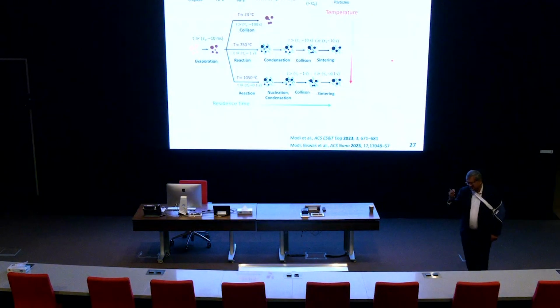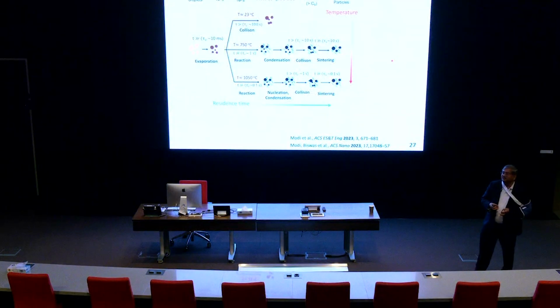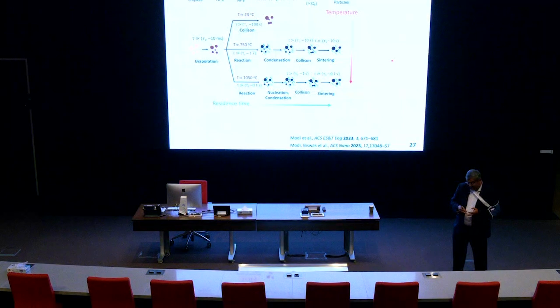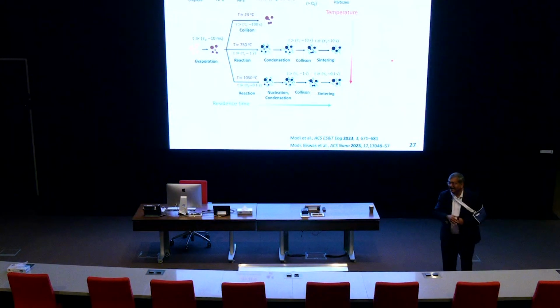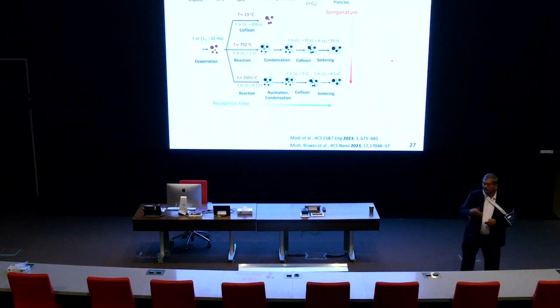So this creates a little bit of a challenge for me to understand. Yes, so in some sense you're absolutely right. Would a pure carbonaceous particle sinter, right? Obviously, if the temperature is high enough, but would it reach that state in a pyrolysis reactor? Now, in full-scale systems, in batch systems, they observe this all the time, even while making carbonaceous material. And it might be partially pyrolyzed with some of these condensables, or these intermediate species, creating these to stick together and sinter. What we did in our sintering experiments was just a single run through and track the surface area. But you're absolutely right. To get a detailed understanding of sintering, I need to couple the chemistry. And it is indeed a function of the chemistry, but we haven't really gone into that. Maybe a next step would have to do that. But it's a good point. Yeah.